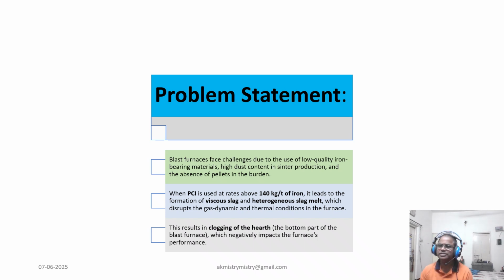Modern blast furnaces are under constant pressure due to raw material constraints. The use of low quality iron bearing material, which is backed up by excessive fines in sinter and absence of pellet, contributes to inconsistent burden quality. And on top of that, the PCI rate exceeding 140 kg per ton of hot metal can lead to a viscous and heterogeneous slag. This disrupts the gas flow and heat distribution in the furnace, resulting in one major issue, choking of hearth or hearth clogging, which ultimately hampers the furnace performance very badly.